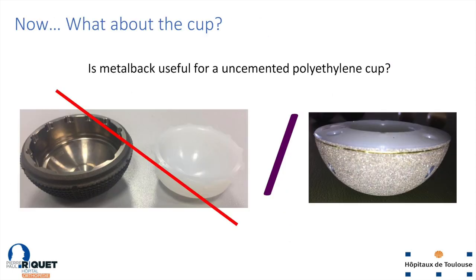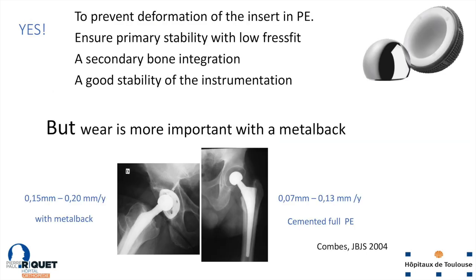I've talked about increasing head size and the possibility of dual mobility, but we still have to think about the cup. If you increase head size, at some point you won't have enough polyethylene. Some implants recently put on the market use a very large metal back with a very thin poly. If the poly is too thin, you risk going back 20 years and exposing patients to wear again, despite in vitro studies. We still need adequate material behind the cup, because in our opinion it can prevent deformation of the insert.